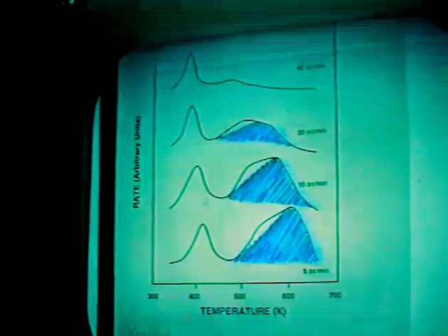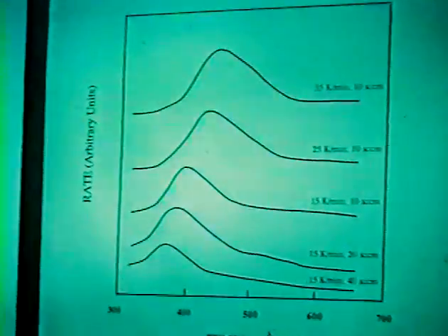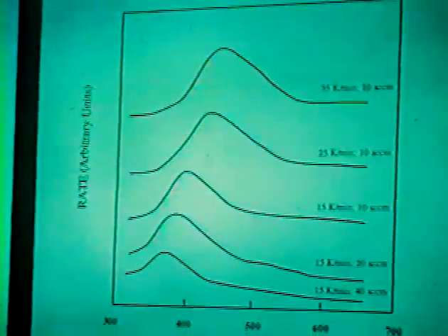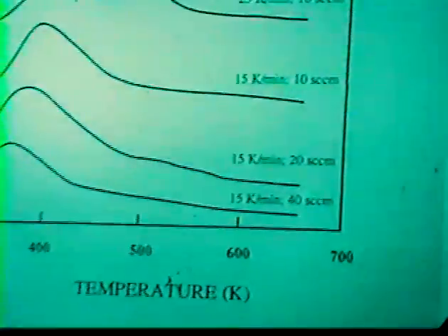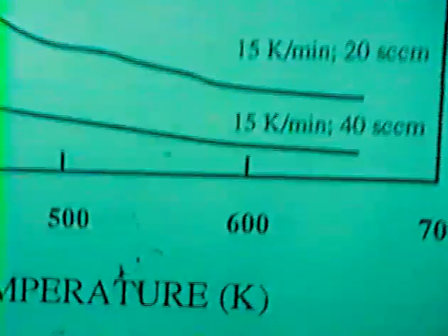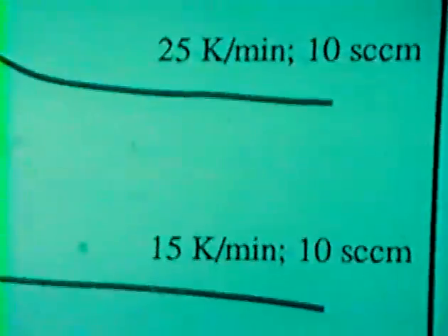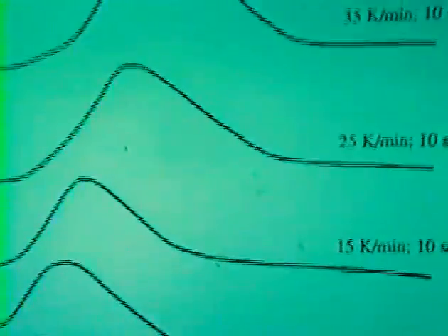That suggests that if the intensity ratios change with either heating rate or space velocity, then that is a clue that you potentially have subsurface sites. Based on these results, we would conclude that there are two surface sites, this low temperature surface site and then the smaller peak here, and there is a subsurface species which is highlighted in blue. That seems to decrease with increasing flow rate. It also changes dramatically with increases or changes in the heating rate.